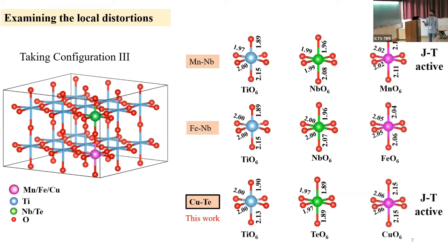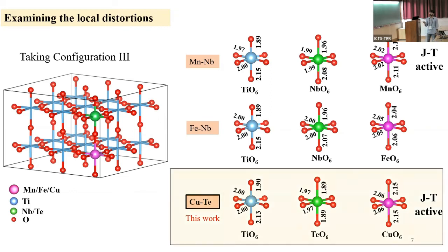Next, if one sees the manganese and copper octahedra, one sees that the axial directions are way longer than the equatorial ones, showing that Jahn-Teller activity is present at the copper site and manganese site. But since iron 3+, which is a d5 system, is not Jahn-Teller active, there is no distortion at the iron octahedra. So this work established the efficacy of using copper and tellurium, which helps in retention of these polar ferroelectric distortions. Now, saying that ferroelectric distortions are sustained in the system after a doping strategy of 11%, we